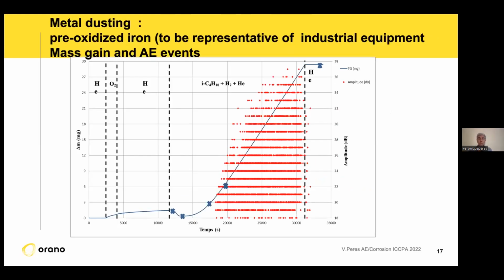So I show you the global experiment we have done in the SEP equipment, with the mass gain in blue here in this system, and the amplitude of the bursts we acquire during this experiment. First of all, we make the heating under helium, and then in situ we make the oxidation under oxygen, which is parabolic. When we change the atmosphere, because we don't want to have oxygen and isobutane in the same atmosphere, it's very dangerous, we do that under helium. And then we begin to treat the sample under isobutane plus hydrogen and helium.